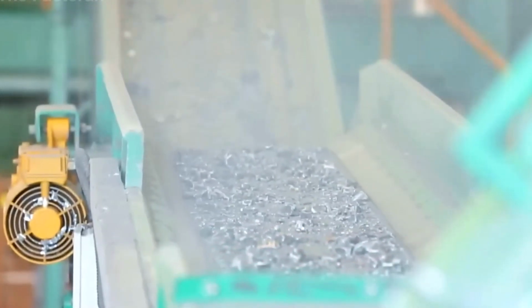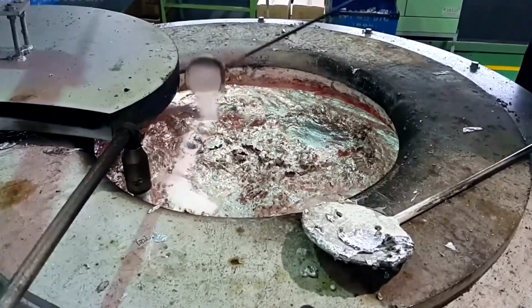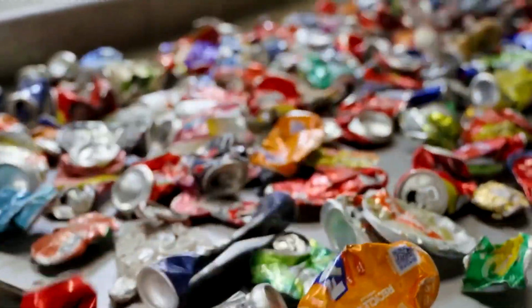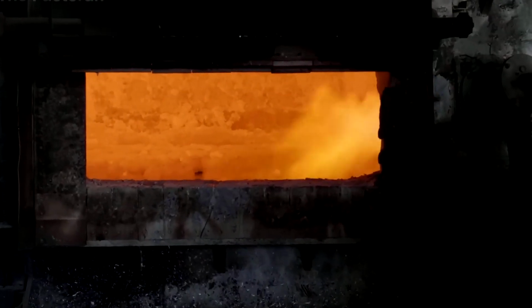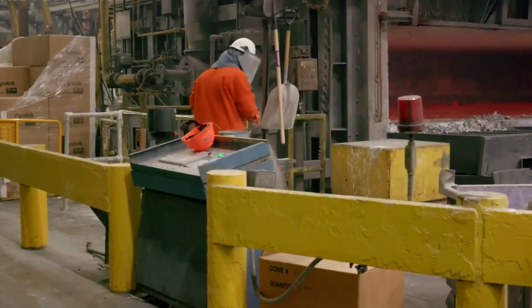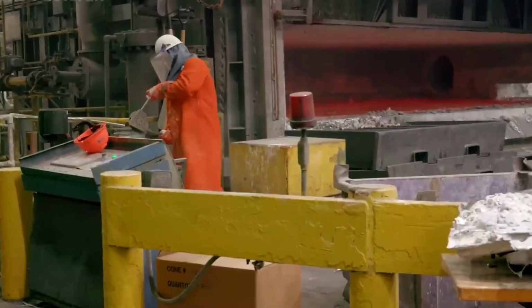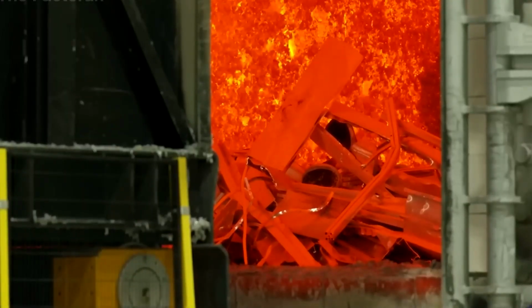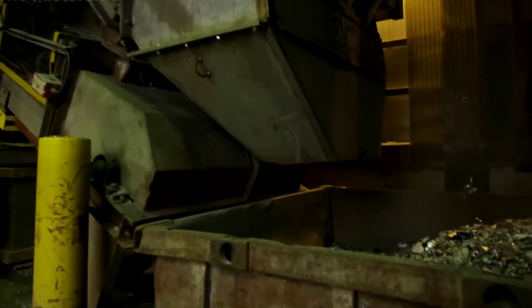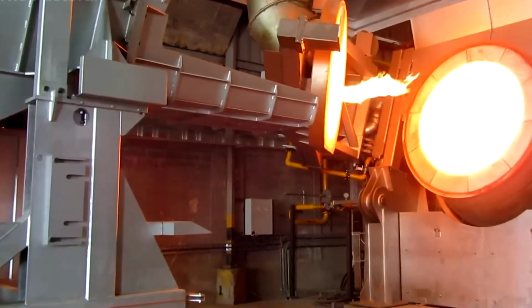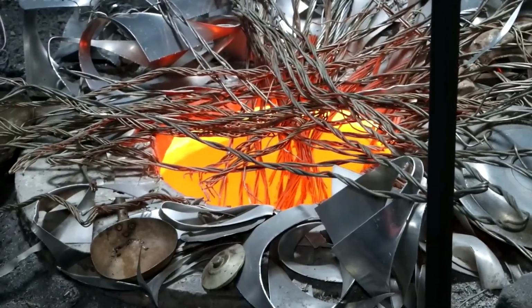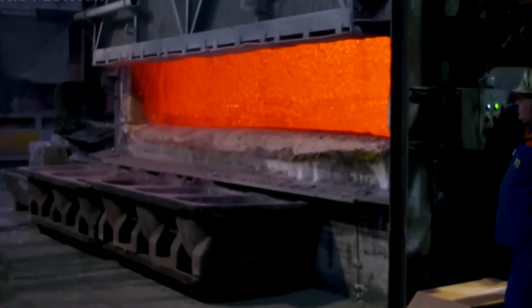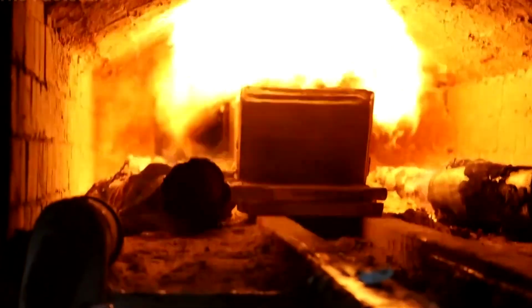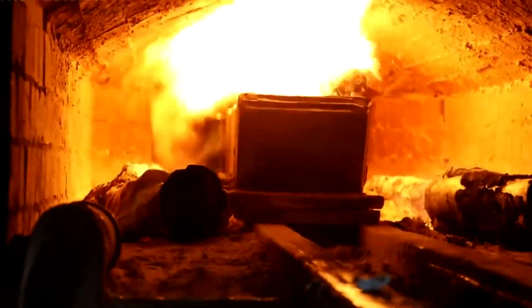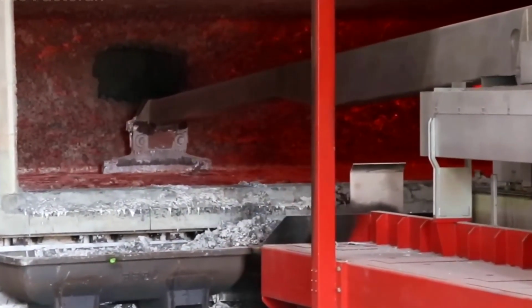Even after the aluminum has fully melted, it still carries invisible ghosts from its past. Countless hidden impurities, oxides, furnace dust, paint residues, and even oils left over from its previous life cycle remain suspended within the molten mass. To eliminate these contaminants, a refining process begins directly inside the furnace. The most common method is fluxing, which involves adding a special agent into the liquid aluminum. As it reacts, the flux bonds with impurities, gathering them into a light floating dross layer on the surface. This metallic foam is then skimmed off, either mechanically or by hand, leaving behind cleaner, more refined metal.